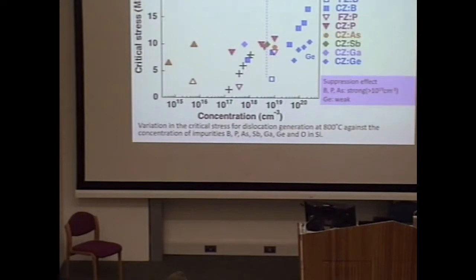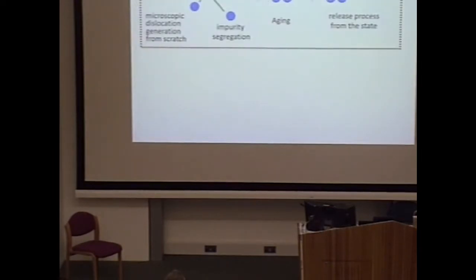So just say that, by these impurities, dislocation generation is suppressed. And this is the background of the critical stresses. So dislocation is introduced from scratch. And during the heating stage, some impurities come to dislocations, just say the segregation, and also make some aging effect. And then under the stress, the dislocations are released from the state.